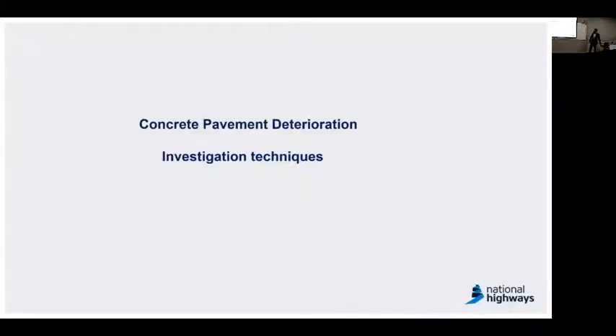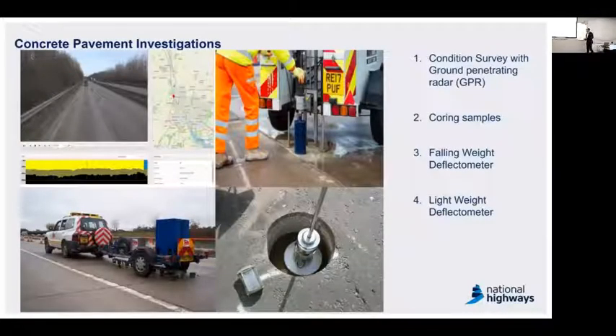Now I would like to talk a little bit about the investigation techniques. Michael has discussed quite a lot about the advanced end-to-end digital approach, but these are very basic points that we normally use for investigating our concrete asset. The one on the left is the visual condition survey, which is carried out at traffic speed, which means we can capture ultra high precision photographs of your network, corresponding to your map. You should be able to see exactly where you are on the map. It also comes along with another feature, GPR, which is ground penetrating radar. On the map here, you see the relative thickness of different layers of the pavement. So it's quite easy to get the condition of your pavement using the traffic speed automated vehicle.